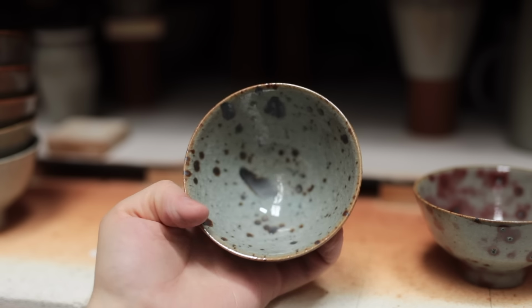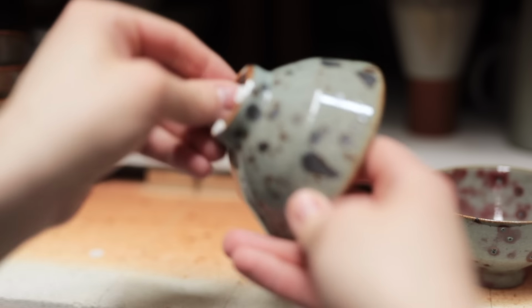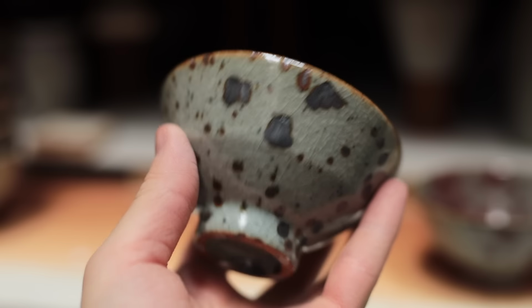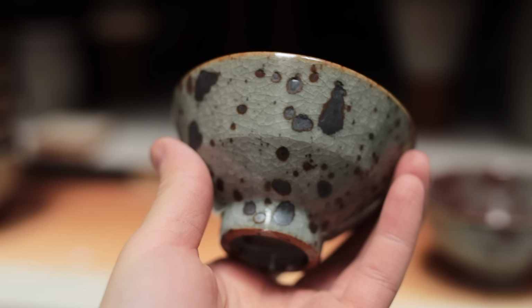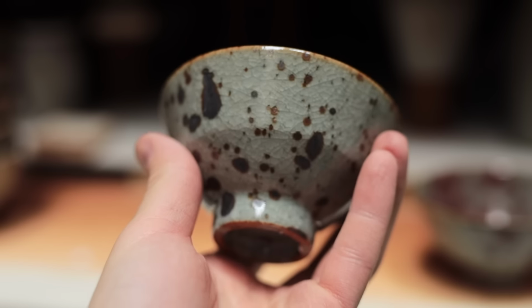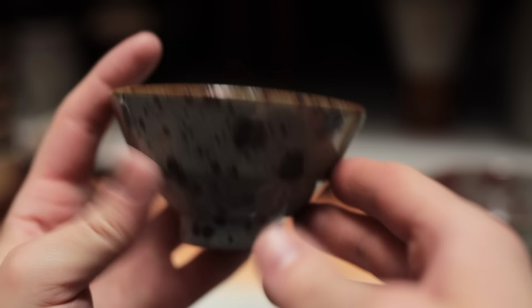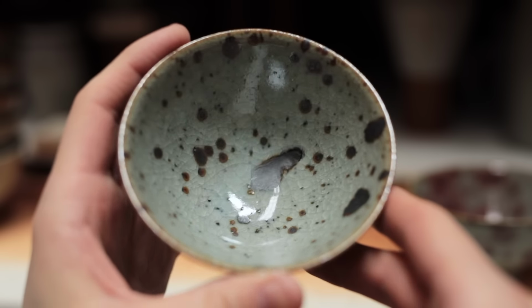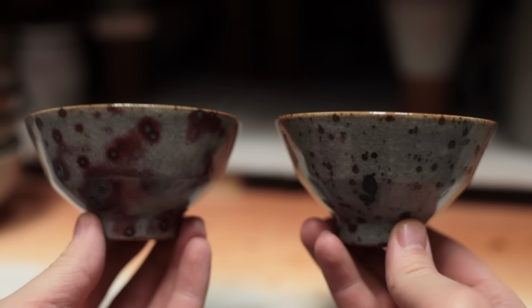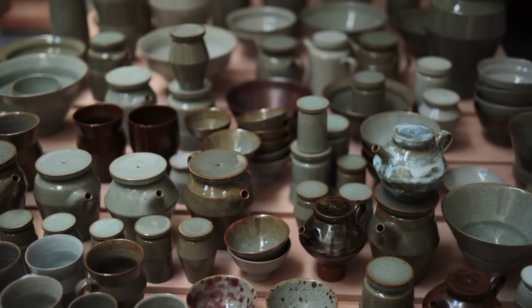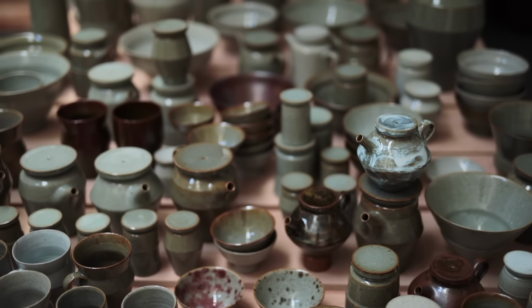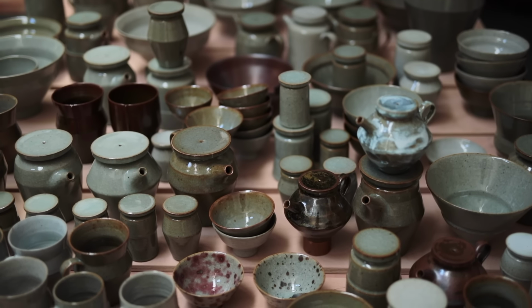As for the steel hammer scale bowl, it too has changed a lot. There are now much larger blots of iron that have really flowed down the surface. I love when you can see cavities where the metal has flowed out. I think there's still too many inclusions in both of these, but as a one-off pair and experiment, it all went unusually well. Here are the rest of the pots from this kiln load, but those two bowls aren't quite